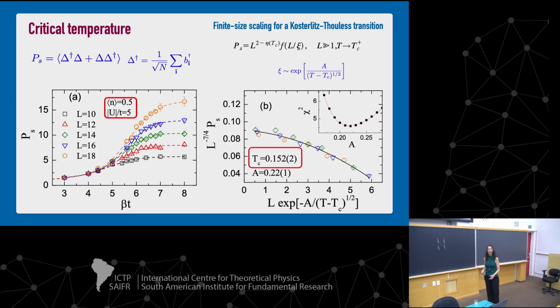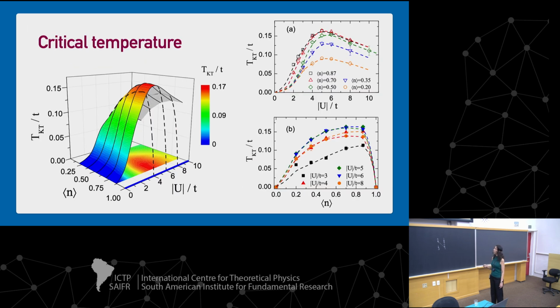So it's a lot of work, computational, to extract a number which is the critical temperature. And then this was done for a value of U, a value of density, and we have to do this for different system sizes to obtain a collapse like that. And then we probe different values and see which one best adjusts to extract the critical temperature. And so he's done this for different values of U, different values of density, and came up with this nice phase diagram. Oops, let me come back.